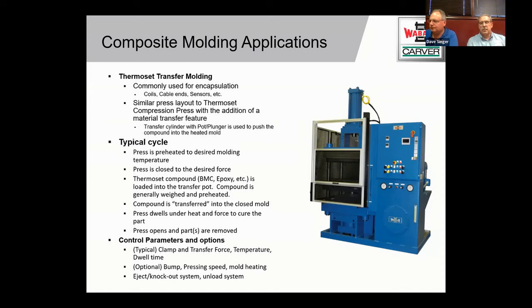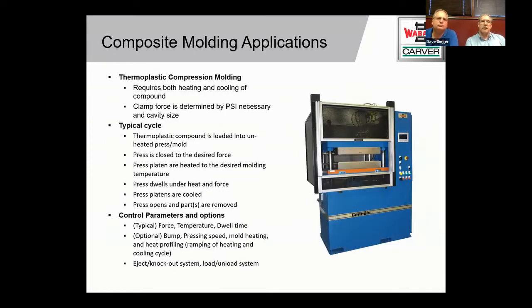And what makes transfer appealing over an injection machine is that you're filling this material with fiber, different lengths of fiber. Now you can use the transfer to inject that material instead of having to go through a screw or anything like that. And these normally are in preforms of some nature that are dropped into the transfer cylinder after the clamp is shut and at temperature. Anything else to add on this one, Joel? I don't think so. Let's go to the next slide.